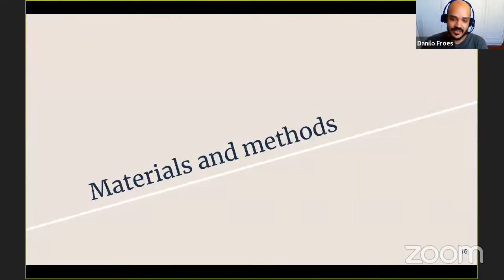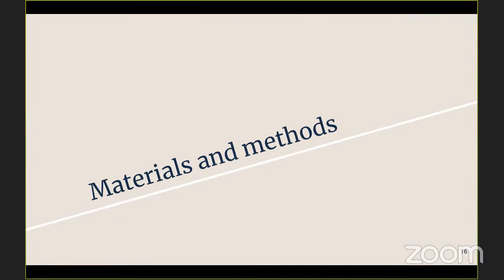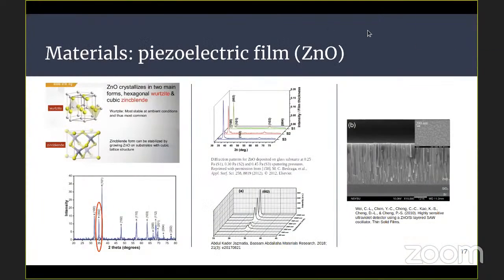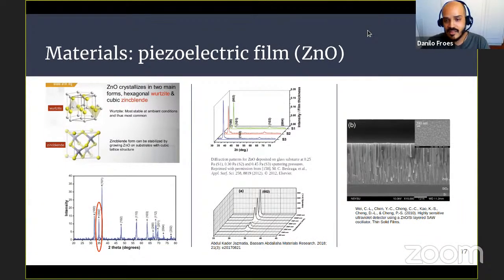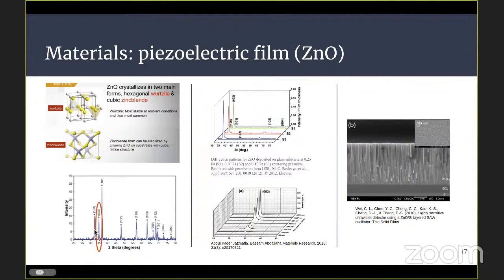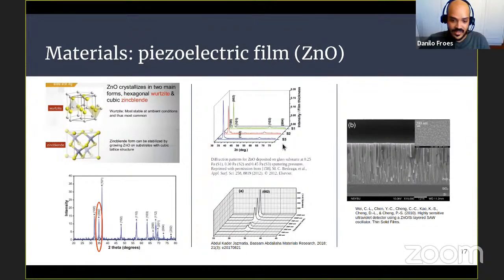Speaking about the materials and methods, in order to do the experiments we wanted, we needed to choose a piezoelectric material and a magnetostrictive, magnetoelastic material. We've chosen the piezoelectric material to be zinc oxide. Zinc oxide is a typical material used in surface acoustic wave devices in the literature, so that's why we chose it. It can have several crystalline forms. The direction with the highest, most effective piezoelectric coefficient is the 002. Here we are just showing some examples always seen in the literature.